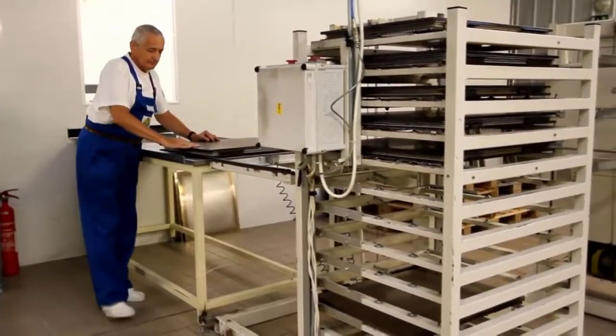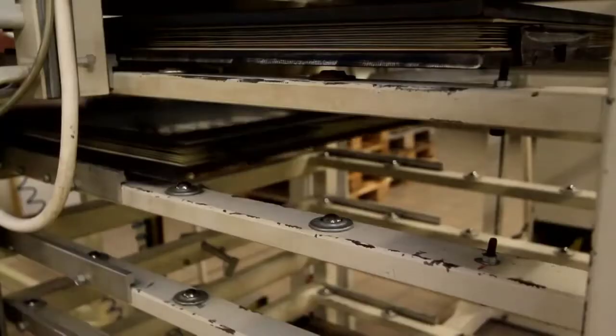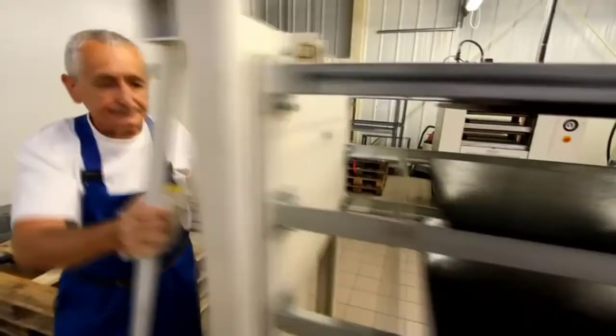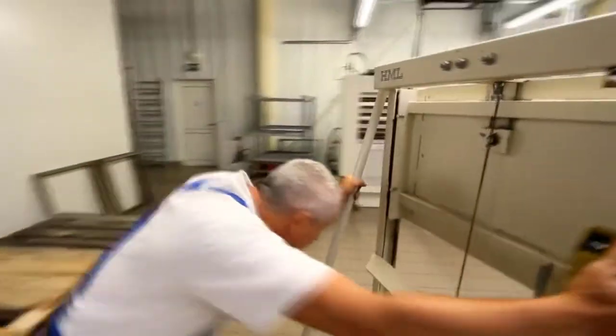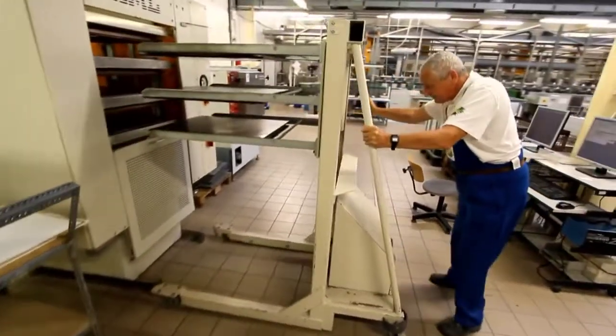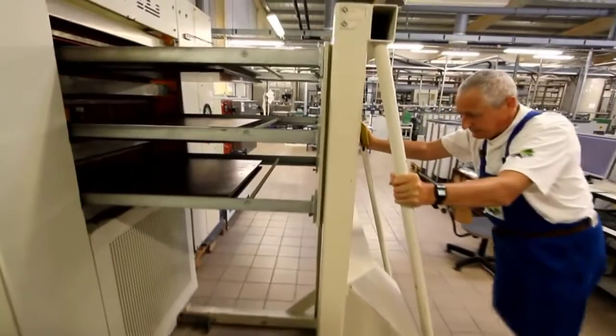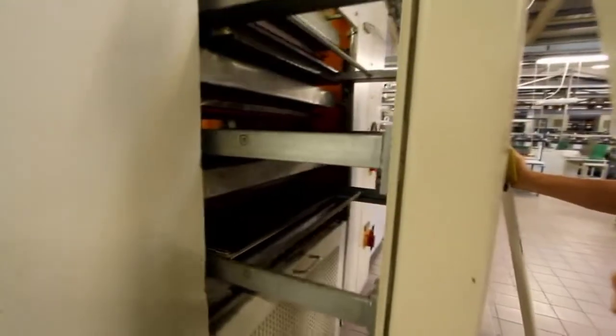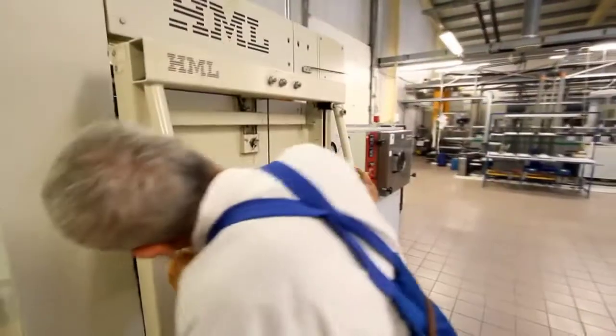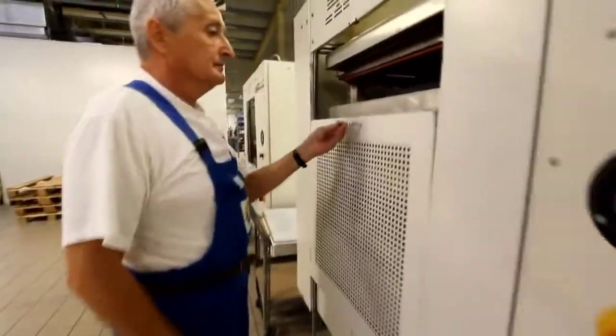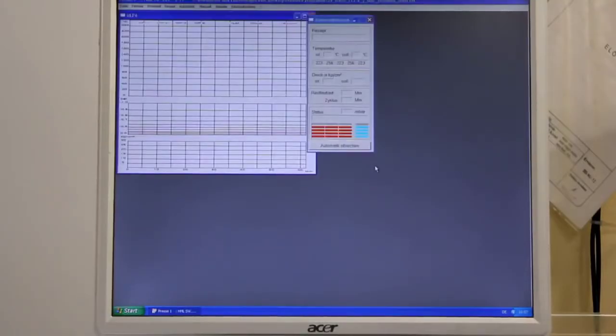The press operator collects 3 stacks on a loader and loads them into the bonding press. This press uses heated press plates and pressure to bond the layers of the PCB together. The heat melts and cures the epoxy resin in the pre-preg, while the pressure bonds the PCB together. The process is computer controlled to build up the heat and the pressure correctly, hold it, and then to cool the press down. In this way we ensure a permanent bond that will last the lifetime of the PCB.